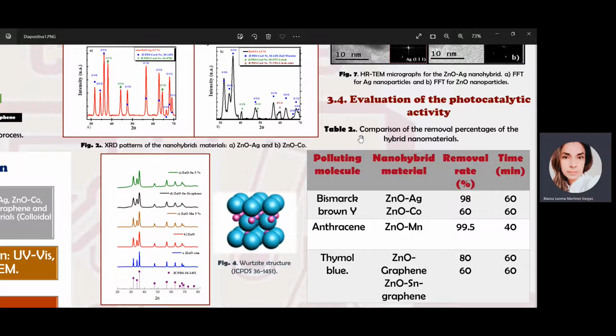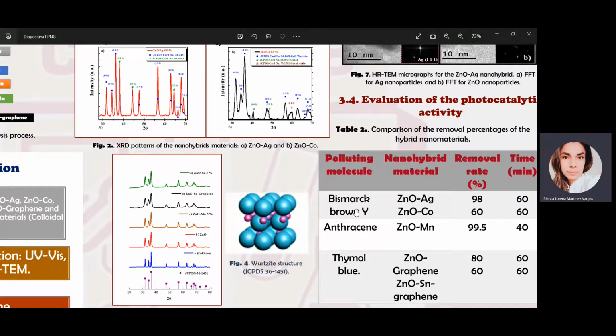Finally, in this table, the results obtained from the photocatalytic evaluation of the synthesized hybrid materials are shown. Three different molecules were used. In this case, Bismarck brown dye was used, and the maximum removal rate was presented with zinc oxide with silver in 1 hour. For the evaluation of degradation of a synthetic organic compound such as anthracene, the hybrid nanomaterial zinc oxide with manganese was used. This nanomaterial achieved 99.5% degradation in 40 minutes.